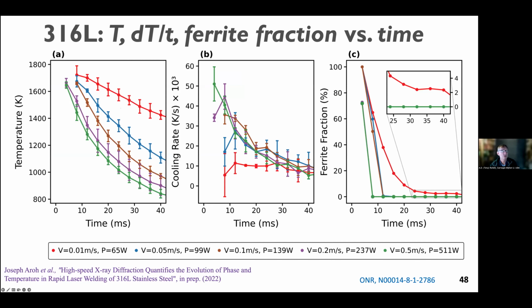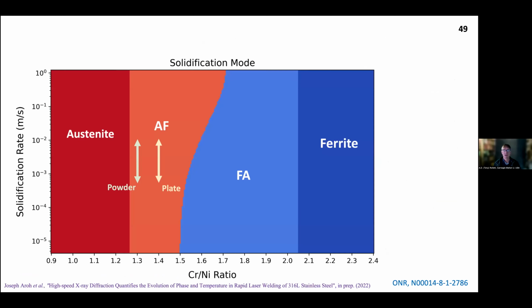And so these curves here are just showing you different temperature versus time histories for different combinations of power and speed, which give you clearly different cooling rates, from slow, from the red one, to as fast as we can manage for the green. And what we were able to establish pretty quickly, so that's cooling rate in the middle, and then ferrite fraction over here, is that there were measurable variations in that ferrite fraction as a function of time and as a function of cooling rate. So to what extent is this understandable? The answer is it should be understandable. And in terms of, as I said, phase relationships.